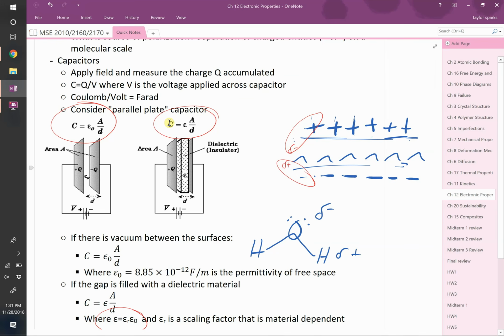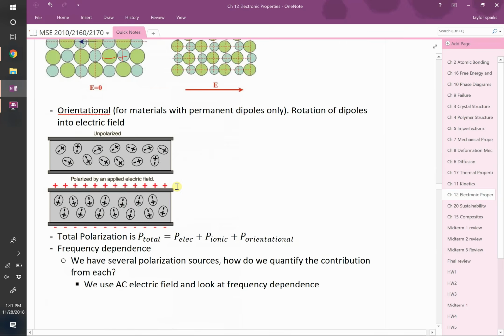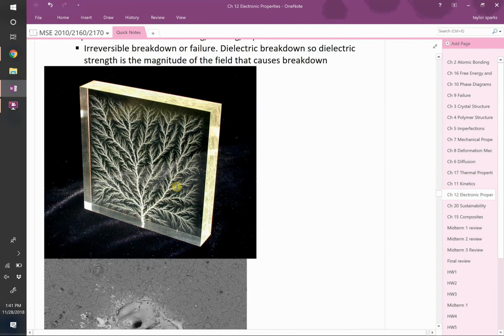But there's a problem. If you go too high, you create lightning. Lightning is just dielectric breakdown of air. So this is not air, this is glass, but it looks the same because it's the same phenomenon. In this one, they put one electrode, and the outside was probably coated with metal, like a metal tape all around the three other sides. And they just increased the voltage between the outside and the probe until you had such a large electric field that you started doing what Josh was alluding to earlier: you have your filled valence band, empty conduction band. Under a large enough field, you'll actually strip electrons across that band gap, and you'll strip a lot of them.